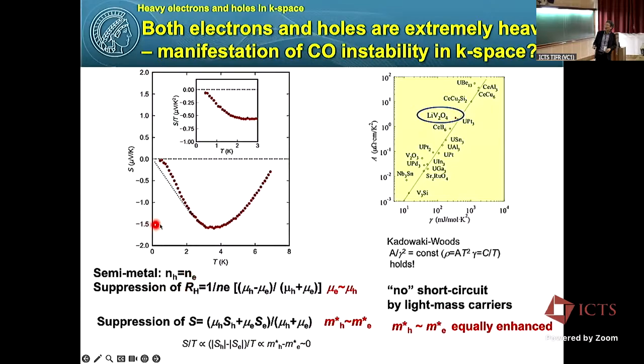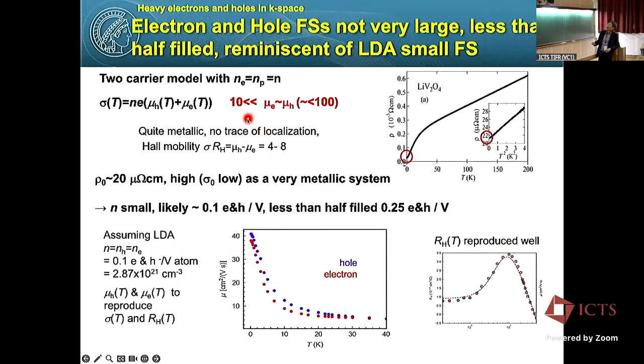Now, assuming the number of electrons is equal to the number of holes, these observations tell us, first, that suppression of the Hall effect means the Hall coefficient is the difference between the hole mobility and electron mobility. So the electron mobility and the hole mobility must be close to each other. But that's kind of obvious. And the Seebeck effect is a mobility weighted average of the Seebeck effect. So therefore, it is roughly the difference between the hole Seebeck and the electron Seebeck. And that going to 0 means their mass is almost the same. Again, we have both electrons and holes, but they have the same mass, almost the same mass. And of course, that's quite consistent. They follow quite well the Kadowaki-Woods relationship, and no short circuit by a light mass carrier. So equal mass. And the last point I want to make is actually related to the magnitude of the resistivity.